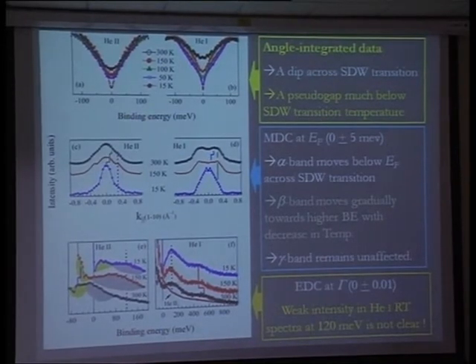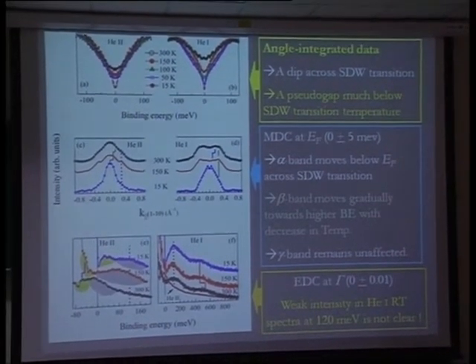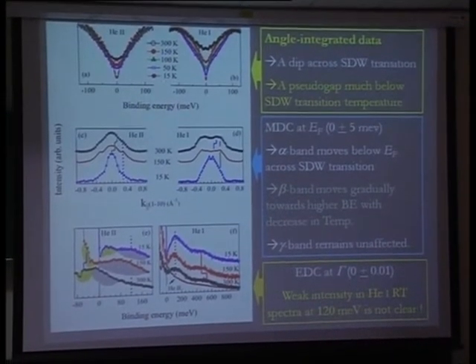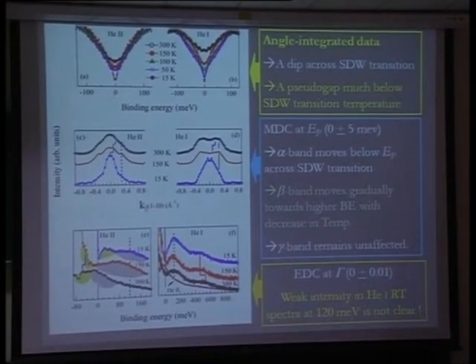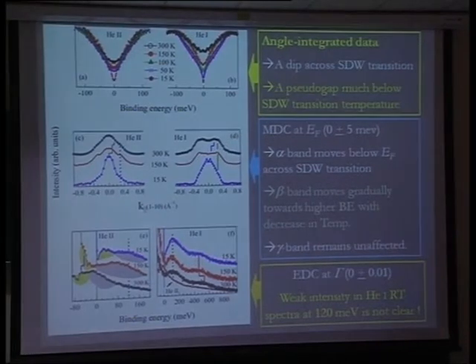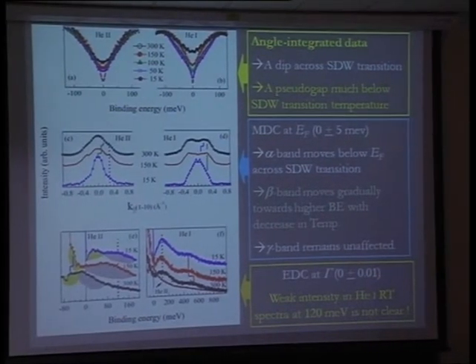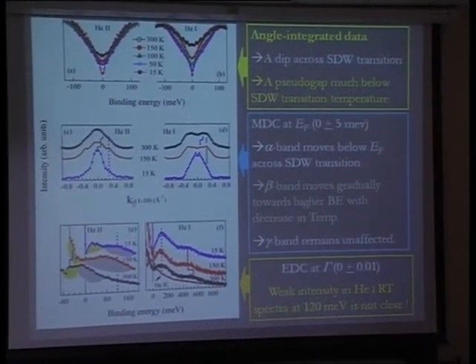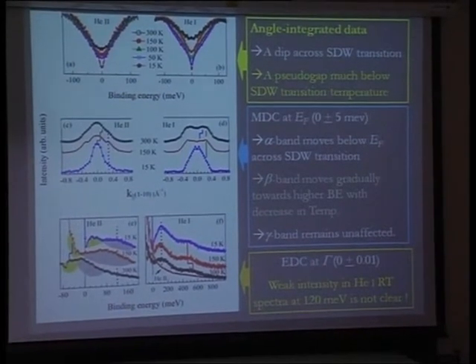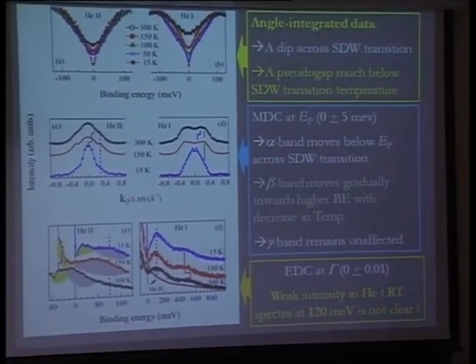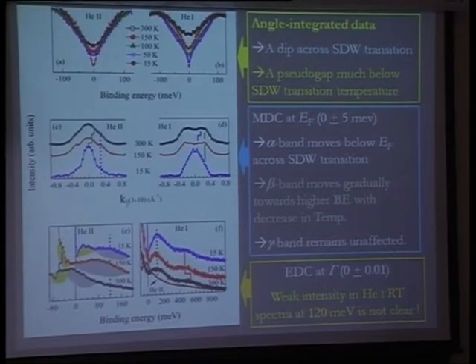This is the most important plot that you can see. This is the angle integrated data with very high resolution, very high meaning 1.5 millivolt. So in helium 2 and helium 1, you can see that across the spin density wave transition, the spectral weight at the Fermi level has a sharp change.